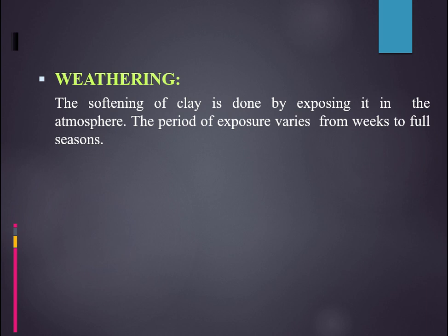And also the soil should be turned over at least twice, and it should be ensured that the entire soil is wet throughout the period of weathering. And also, to keep it wet, you may spray water as often as necessary, and hence the plasticity and strength of the clay will be improved by exposing this clay to weathering action.